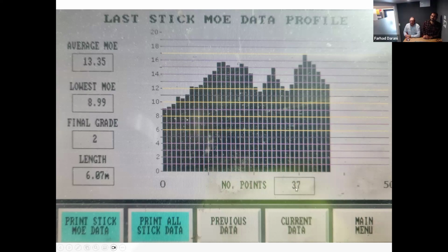This is a picture of the structural profile of a single length of timber. There are 37 points that are graded here, and every one of these bars is about 164 millimeters of that length of timber. So you can see the huge range we have in the structural portions of a single stick of timber, and that's because we're dealing with a living product, as timber is. The highest grade here got up to an SG 17, the lowest was an 8.9, and the average was 13.35.